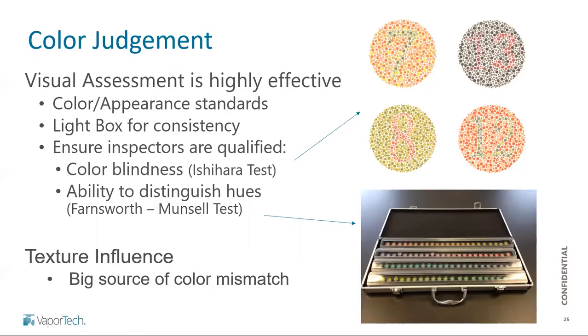One last thing I want to say, and it's been a very important learning over my 20 years of working in decorative coatings, is how important the influence of surface texture is on color mismatch and judgment. I can't stress this enough. One thing we haven't really talked about is that these coatings are so thin, they can be applied on any kind of texture, whether it's brushed or a matte texture, and they're thin enough that they don't really change the texture. However, those textures can have a huge impact on the way you perceive color.